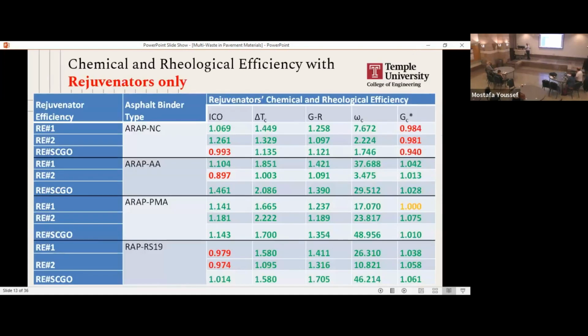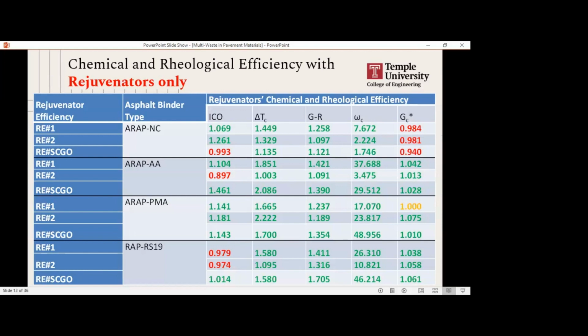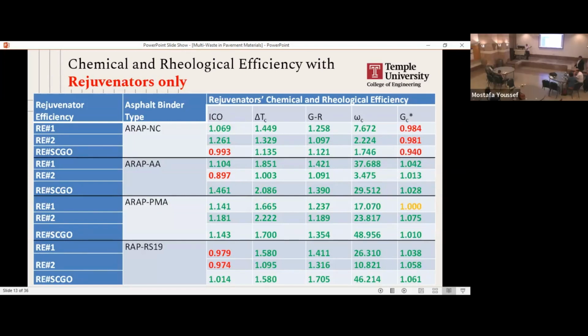Then the bio oil itself, we started looking at, does it really have a rejuvenating effect or not? So what we did is we compared our developed oil to market-ready oils. The way you look at the rejuvenating effect is you evaluate the change in the binder before the addition of this additive, and after the addition of this additive, then aging it, then testing.